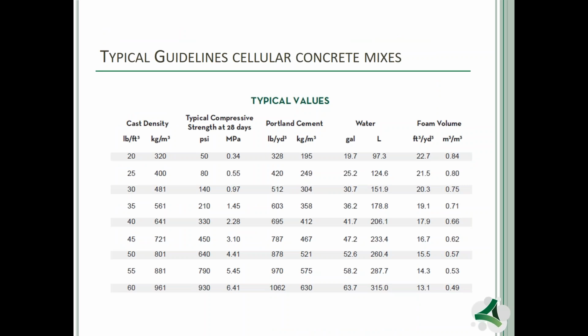As I mentioned before, with the cellular concrete, it is not designed to be the wearing surface of the project. Cellular concrete replaces traditionally compacted backfill. So if we take a look at traditionally compacted backfill at what, 50, 80 PSI, and if we compare that, for example, to a 30 pound per cubic foot scenario, that material will give us 140 PSI. So we are well ahead of the game.